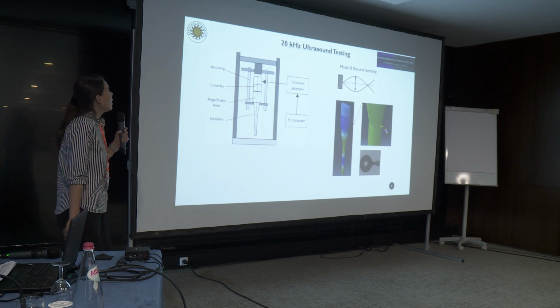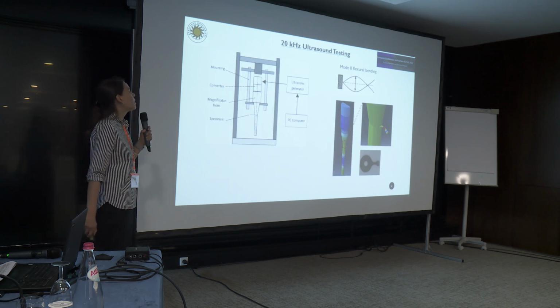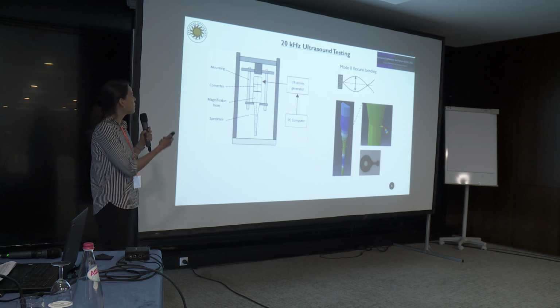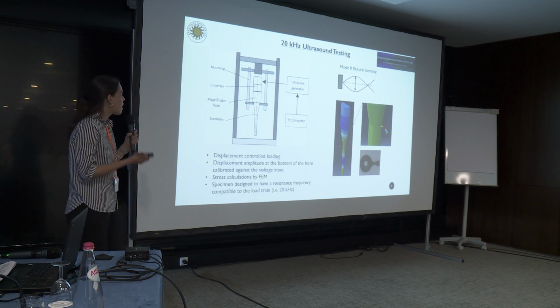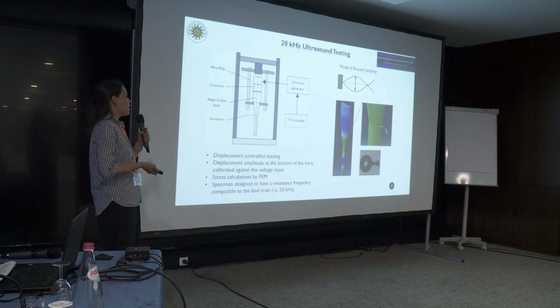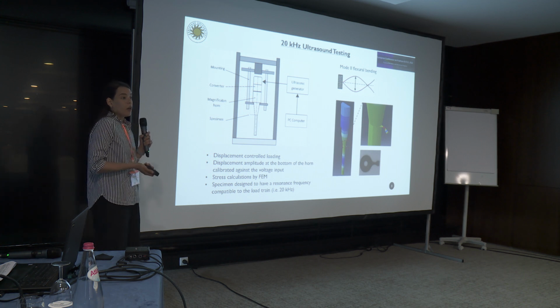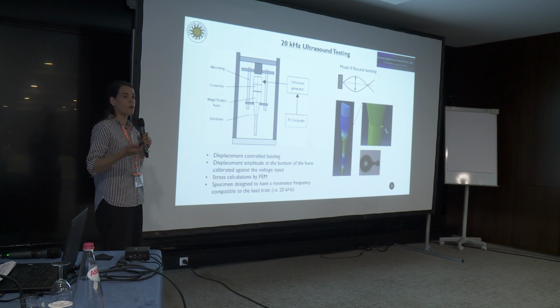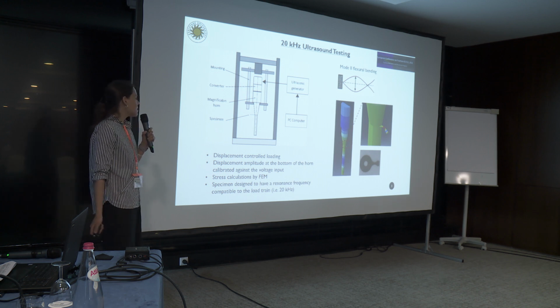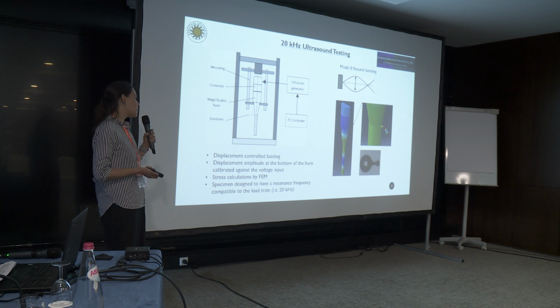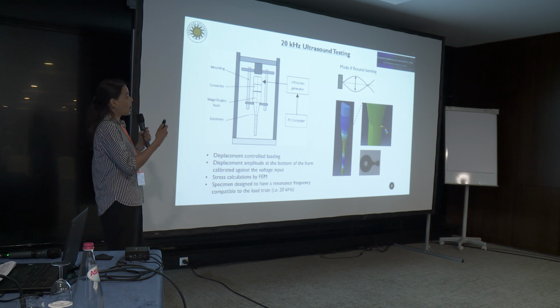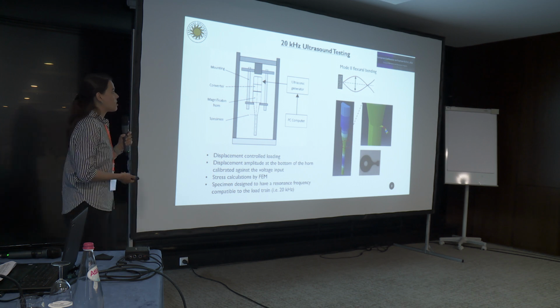So we have the setup here. At the ultrasonic generator, an electrical signal is produced, and through the booster and the magnification horn, it travels to the specimen as an oscillating vibration. It is a displacement control loading, while the displacement amplitude at the bottom of the horn is calibrated against the voltage input. We use FEM calculations in order to have an image of the stresses. My colleague presented these results in detail, while the specimen is designed to have a resonant frequency compatible with the load train, and also to be sure that we are in the mode 2 flexural bending conditions.